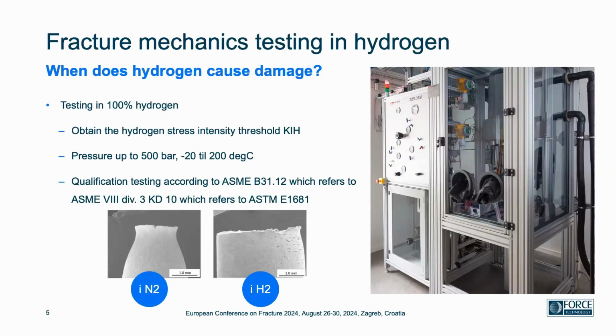So back when we started with the involvement in the hydrogen industry, as we are an RTO that needs to deliver service to the industry, we decided that we needed some test facilities for testing in hydrogen. There are several ways of testing. The first one I'll talk about is the stress intensity threshold factor that can be tested with a constant displacement or constant load test. And the equipment we have can be pressurized up to 500 bars, and the temperature is between -20 and 200 degrees Celsius.